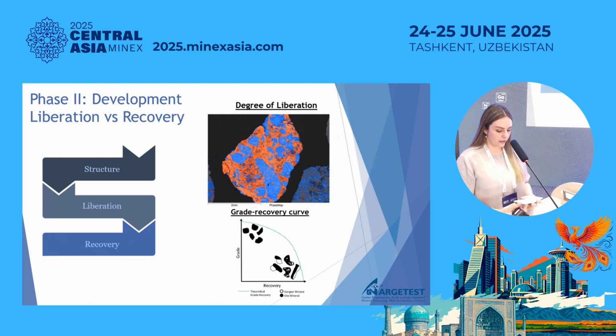And that brings me to the grade-recovery curve. So here you can see on the x-axis is the recovery of your mineral, and on the y-axis is the grade. So everything that is above this curve, so on the upper side, it's not possible physically. So you cannot be on the upper right-hand corner where the recovery is really high and your grade is really high. So it actually is kind of a trade-off relationship. So you have to choose exactly where on this line you want to be in terms of your recovery and grade. And what's important here is that you can actually get the theoretical grade-recovery curve from your mineralogy data.